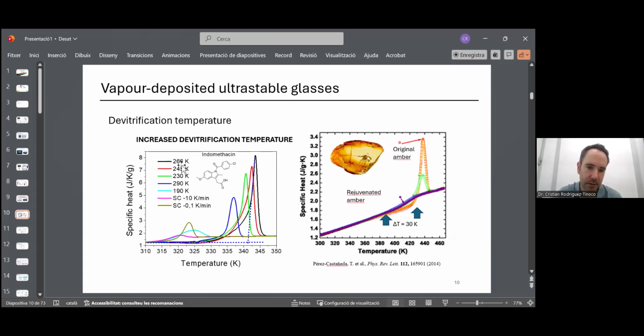On the other hand, if we grow this indomethacin glass at 266 Kelvin, which is exactly 85% of the glass transition temperature of indomethacin, we have this devitrification peak, which takes place at much higher temperature compared to the glass that has been formed by cooling from the liquid. You see here a larger devitrification temperature, and the area under the peak is also larger, which means that the change of enthalpy between the glassy state and the liquid state is also way larger, which means higher thermodynamic stability.